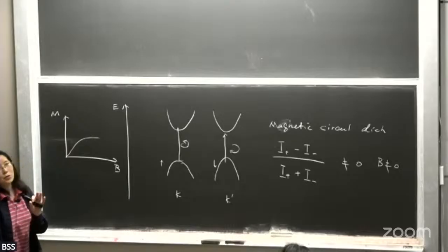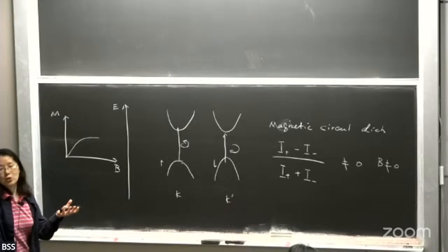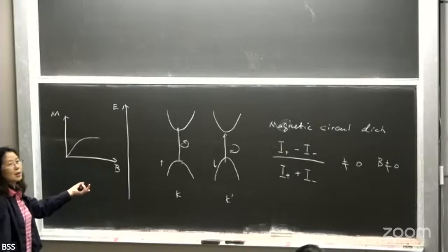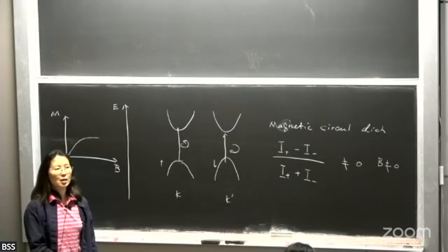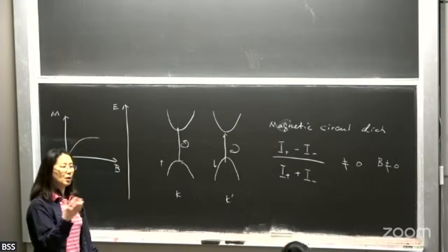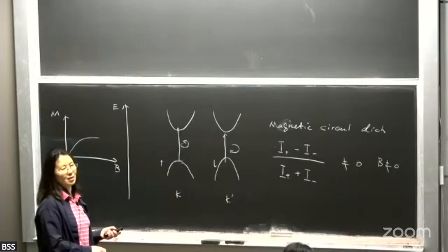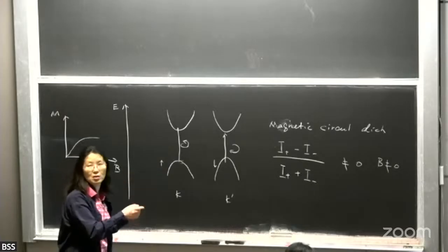Yeah, so this is a very good point. One advantage of optical measurements is the selectivity. You can tune the light color to match the resonance in a particular material. So in this case, we tune the color to match the exciton resonance in a particular layer. If you look at the response at some other frequencies, you don't get this. And this also makes the signal strong, because it hits the resonance.